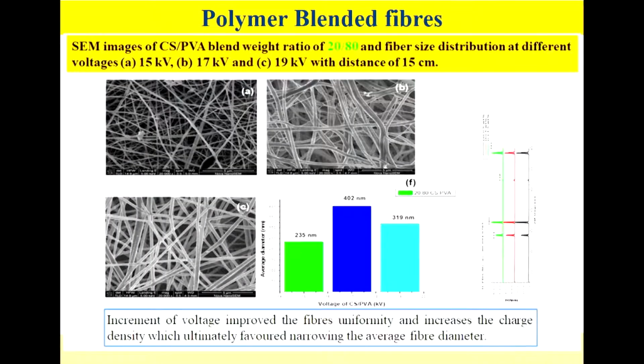And the same thing happens with the chitosan PVA blend when varying the voltage. You can see that as you increase the voltage up to about 19, they reach a critical point where, because of the high charge density in the material, you end up with a lowering of your fiber diameter.